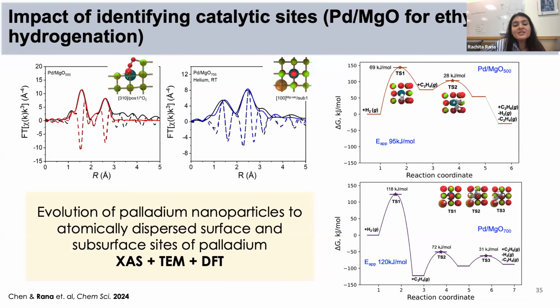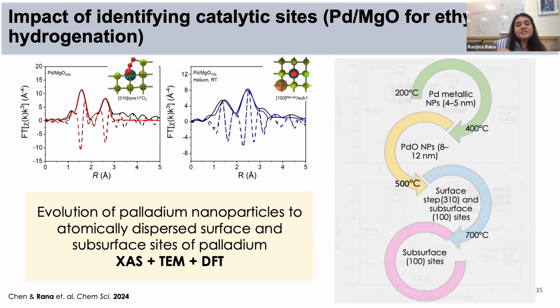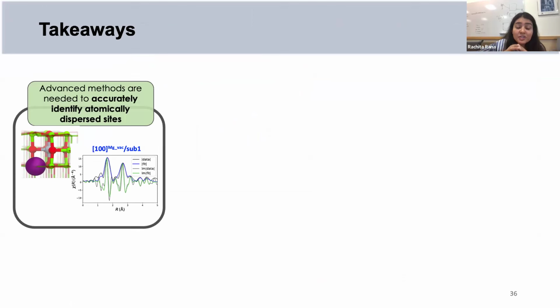So for this, we were able to understand, I mean, there were other details in this, but in the interest of time, I would just try to complete the story where different treatments of palladium particles on magnesium oxide resulted in metallic palladium, and then it went to palladium nanoparticles of palladium oxide, and then a surface palladium site, and ultimately a subsurface, much more homogeneous palladium site. So with that, we went on to use MS-QuantEXAFS on some other materials.